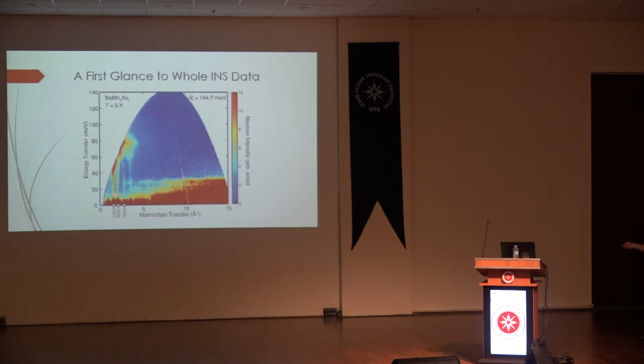As you see in the whole data, there is magnetic information over here. If you see scattering at E different from 0, which is the elastic line, it is magnetic information. This part can also be magnetic, but it is not. As you see, the line increases in intensity as you go to higher theta angle or higher Q values. That is phonons. Phonon structure does that, so that increase is mostly quadratic.